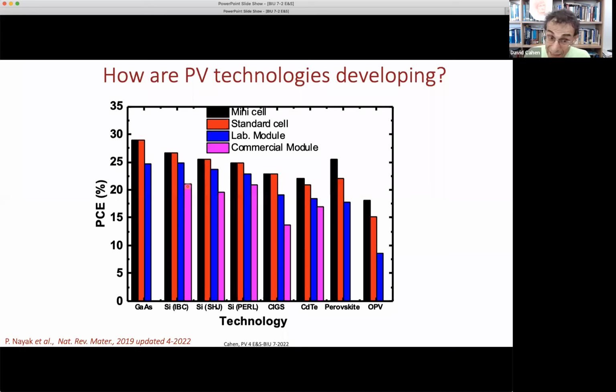So this is the gap between the best cell and the commercial module. And you see the mini and the standard cell have no difference for silicon. Also not for CIGS. For telluride, the mini cell is a bit more efficient. For perovskite, there's a big gap, as for the OPV, although relatively speaking less. And then what about the modules in the lab? We have only modules in the lab here. They're way behind